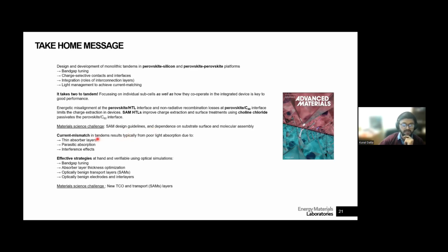Then in terms of the current mismatch, which is a key component of my talk today, we see that there's a mismatch because our absorbers are either too thin, or we have parasitic absorption in the interfacial and charge transport layers. We have optical interference, which reduces primarily the response in the near infrared. And we overcome it by tuning the band gap, by changing the absorber layer thickness, and by working with more transparent charge transport layers, for example the SAMs. And in the case of the perovskite tandems, most importantly for us was the use of very transparent electrode layers and interlayers.